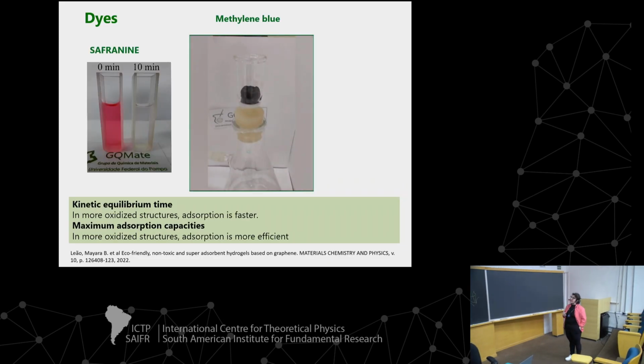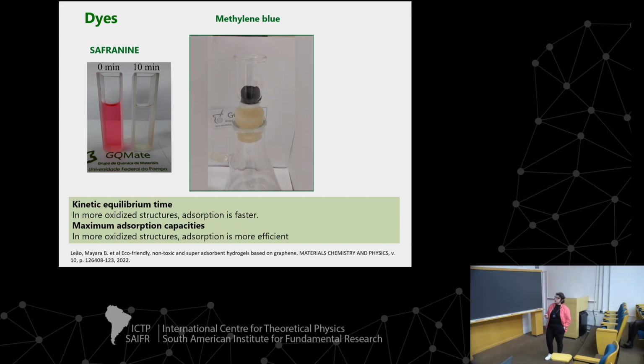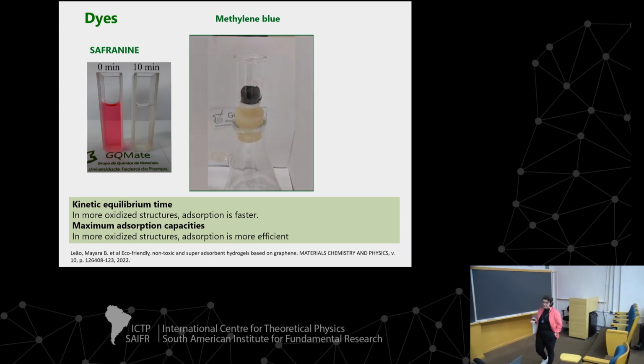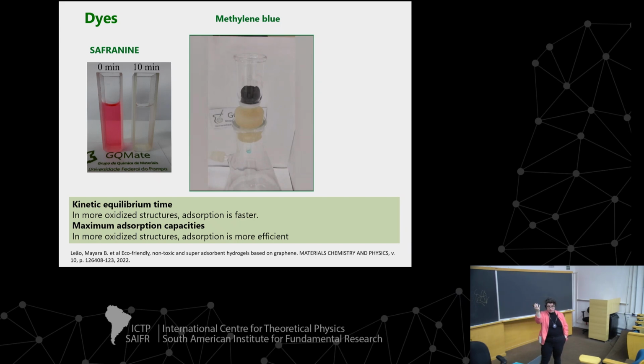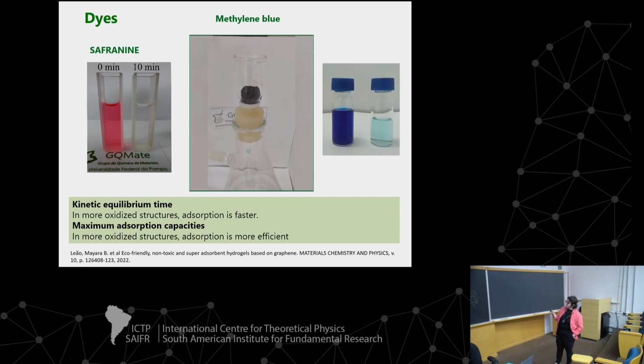Another system is using dyes. We have different works using cationic and anionic dyes in different environments. And today I will show you a highly concentrated methylene blue water solution. And we are dropping it on a membrane, this material, with a flux. It's a pumping. And we can see it is very, very blue in the beginning. In only 1 minute, we can adsorb and transform this highly concentrated pollutant solution. So it's very, very interesting.